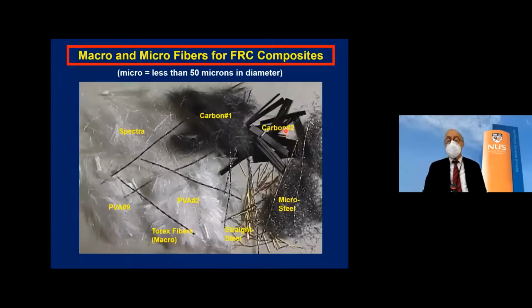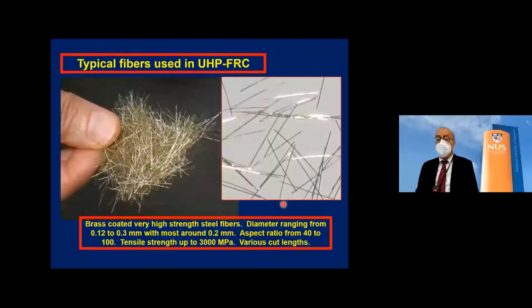And I have also another set of fibers that we could use. It's going to be very modern fibers to use. I like to call anything below 50 micrometer a microfiber. So I have carbon microfibers, I have PVA microfibers, I have even some steel microfibers in the shape of steel wool, etc. So all these are available today if you want to use fibers. And this fiber that I show particularly because we are going to talk about ultra high performance concrete. This is the type of fiber currently used mostly in ultra high performance concrete.